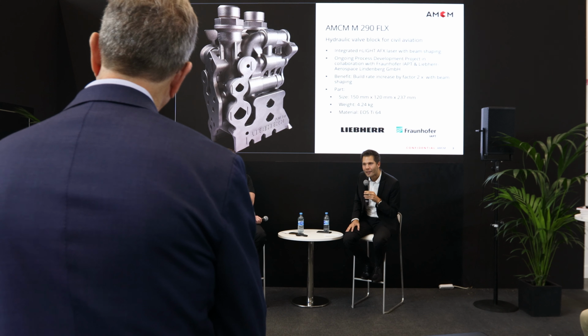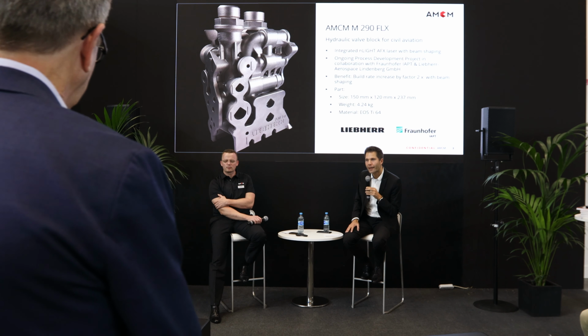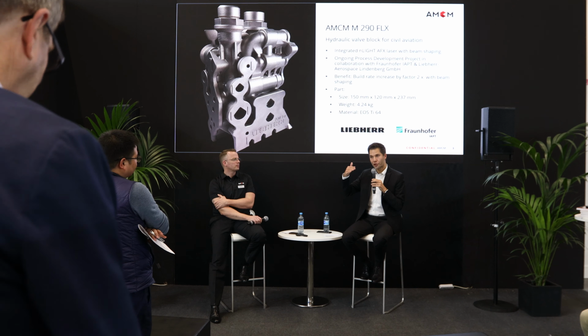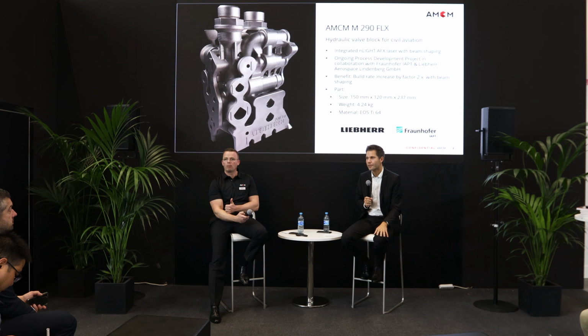Sorry? I just want to know Gauss, ring, and top hat. Which is better? Yeah, with regard to the resulting temperature profile, if you use the ring profile, because of the heat transfer in the ring, this will lead to the effect of a flat top as a temperature profile, which is very, very nice. So the ring is preferable for most cases, not for all, but for most cases compared to the flat top profile. But there is, as I mentioned, a very nice graphic on the website of nLIGHT, which underlines this. And yeah, I'm happy to share that with you after the presentation here.